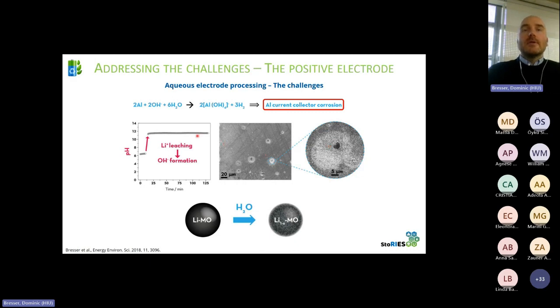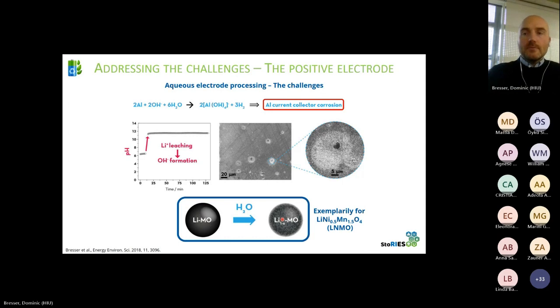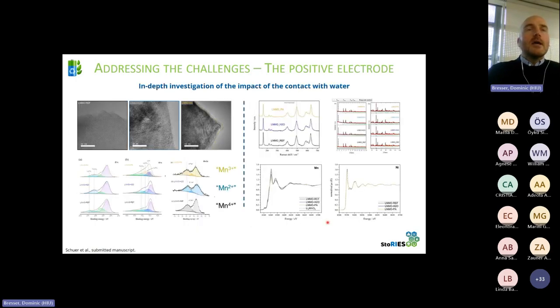The other point, apparently, is that when we're leaching lithium out of the structure, we have changes of the material, largely at the surface, but potentially reaching into the bulk. That is apparently an issue as well, right? So we're not only affecting the aluminum current collector by corroding it, but we're also degrading the material to some extent. And I will talk about this exemplarily for lithium nickel manganese oxide, abbreviated LNMO, a manganese-rich and, let's say, relatively nickel-poor potential cathode material that I think is increasingly investigated now to become the next generation cathode material.